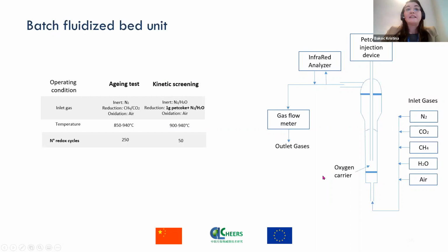The first level of screening was performed in the batch unit, which is the fluidized bed unit that you see here on the right. Oxygen carrier material would be placed on a plate, and then fluidizing bed condition would be achieved by injecting a certain mixture of inlet gases. Two types of tests were performed, namely, first being the aging test to see what was the lifetime of the material in exposure to a very reducing atmosphere of methane, and over a high number of cycles, around 250 redox cycles would be performed. A second type of testing would be with the actual solid fuel injection, where petcoke would be injected to the fluidized bed from the top, as you can see in the scheme on the right.